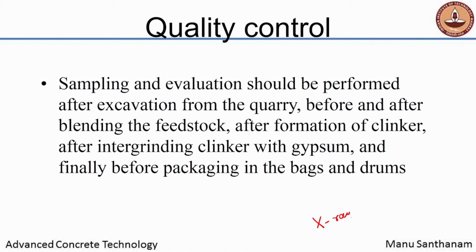Here, in cement manufacture, samples of the proportion of the cement that is to be tested are sent to the quality control lab, okay, inside the cement plant, and there within 5 minutes critical oxide compositions of the cement can be deciphered, and this is done with the help of a technique called X-ray fluorescence. Now, I do not think we need to go into details of this technique.